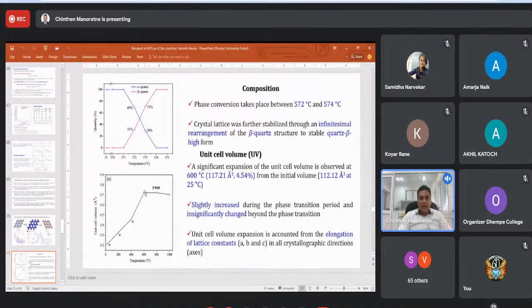After conversion, the change of unit cell volume is very small. So you can see that phase conversion takes place between 572 to 574, and the crystal lattice was further established through the infinitesimal rearrangement of beta quartz. And when you take unit cell volume, a significant expansion of the unit cell volume is observed at 600. Actually, I am not discussing this in detail, because we have published this data. You can refer to these articles. It is available on the website.